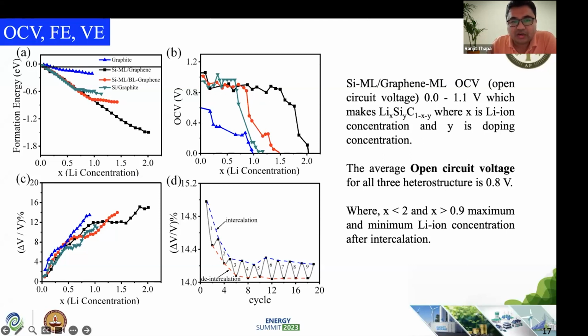is increasing to around 0.8 volt. So that means if you increase more and more silicon, or how much you need to give the silicon, so that your OCV will be maintained, and your overall specific capacity you can increase from suppose 1 to 2 lithium per unit cell. So that means 300 to 600 milliampere hour per gram. So from there you can change from 300 to 600, but your OCV will also increase in that case.